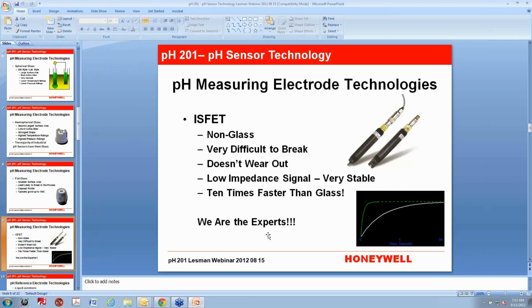Okay, so our last pH measuring electrode technology is the ISFET. ISFET stands for Ion Sensitive Field Effect Transistor. It's a little piece of electronics put into a little plastic body, and has some layers in it so that it's protected, and then it's all melted and heat sealed. It's non-glass, which is wonderful because you can put it in the process and it won't break. It's unlikely that you would break it during a calibration. In fact, sometimes you can even drop it on the floor and it doesn't break, which is pretty nice. It doesn't wear out.